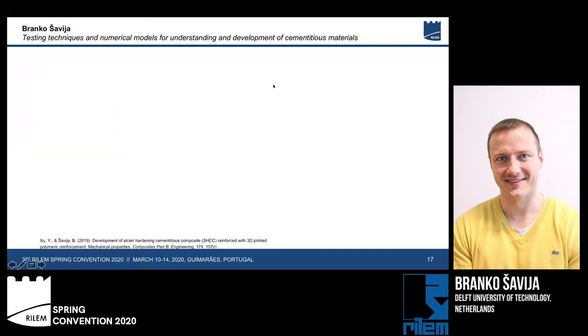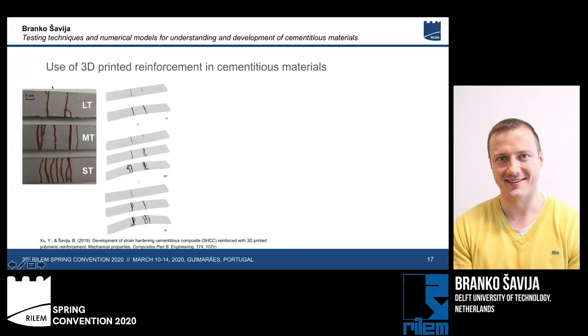So just briefly, some results from this research. On the left-hand side, we have cracks from four-point bending experiments in three different types of reinforcement geometries. With large triangles, we have one or two cracks forming. With mixed triangles, we have multiple cracking in the constant moment region, and small triangles show the same. And our model is also able to more or less mimic this behavior. So we now can use this model, change the geometry of the reinforcement, for example, its volume and so on, and optimize it instead of testing every time a new geometry and seeing what happens.